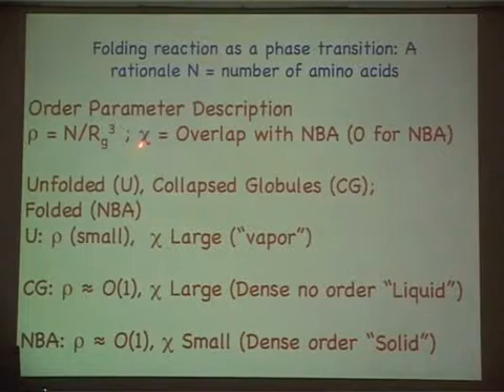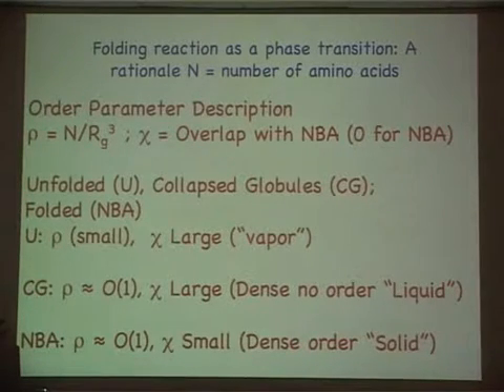And then a second measure, the overlap function, is how much a given conformation resembles the folded state. These are the 2 order parameters that we can think of. There are many more, and I'll come back to that later, which is in fact the problem. So let's look at unfolded, collapsed globule, and folded states. For the unfolded state, rho is small. Why? Because RG scales as n to the 0.6, RG cubed will be n to the 1.8. So rho will be n to the minus 0.8. For any typical value of n, rho is going to be small. Chi will be large. The way we defined it, large chi means that it has very little overlap with the native state. We should have done it the opposite way, but that's not the way we did it.